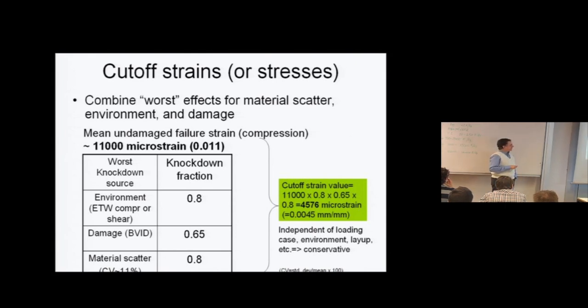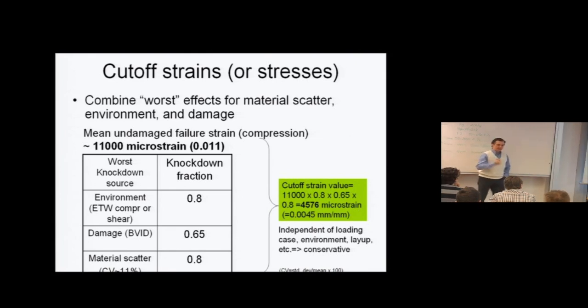For accounting for environment, we have 80% as the multiplicative factor, or a 20% reduction. Accounting for damage, barely visible impact damage, we multiply by another 0.65, or a 35% reduction. This is for the newer materials, not the first generation thermosets I just showed you, which are not as good as this. And then the material scatter to give us the A or B basis. This assumes a coefficient of variation. This at the bottom left here is meant to say CV, coefficient of variation of 11%, which is a bit on the high side, but it's good to cover most cases. It gives you another multiplicative factor of 0.8, or a 20% reduction.